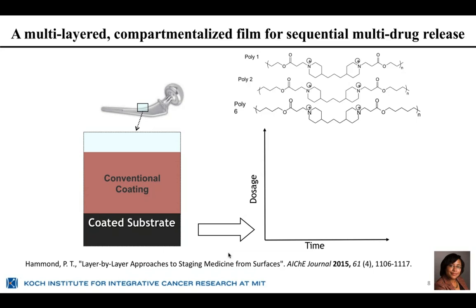On top of that, it turns out that the rules of polymer science, of course, are that you can only put a small amount of this biomacromolecule, for example, in the polymer before you get microphase separation. And once you get that phase separation, you're going to have a more bolus release. Finally, if you introduce multiple components into the film, you end up with all of them coming out in the